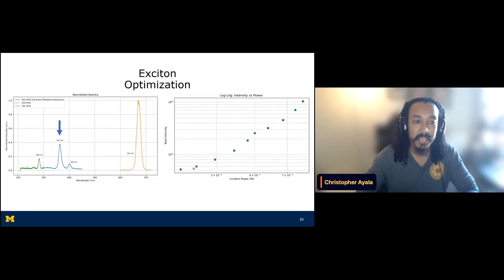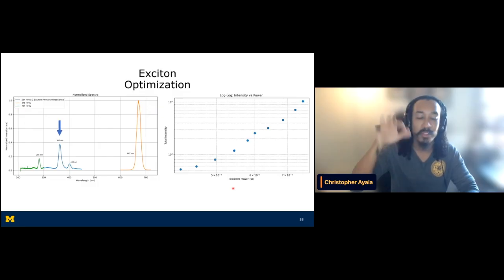What you actually see happen is that during this exciton optimization, or when I look at the exciton, it would follow I to the 3.5, if I'm not mistaken. I didn't include it here, I apologize. But you would actually see that it's about I to the 3.4 or 3.5. And that just means that you can confirm that it takes about 3 or 4 photons to bridge the gap for this material, for the energy gap. I don't have it placed here, but what you would see for the seventh order harmonic is that it would follow some power law, but then it would start tailing off as you increase the intensity, and that would show that the harmonics are now in a non-perturbative regime because it's not following the power law that you would expect.